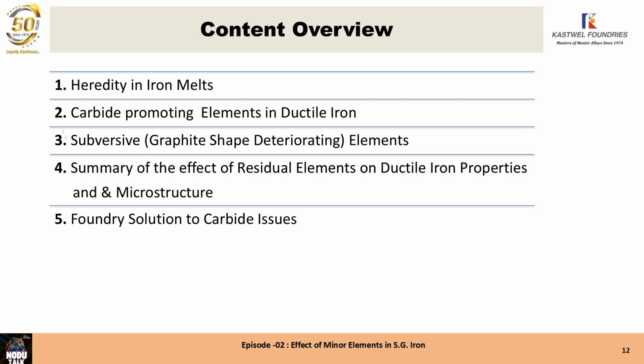We also saw that in order to avoid graphite flotation in any SG iron castings, depending upon the section size, we have a limitation on the carbon equivalent, which cannot exceed the given value for various section thicknesses. We saw this last time. The upper and lower limits depend on the silicon content, which depends upon impact, shrinkage tendency, and so on and so forth.